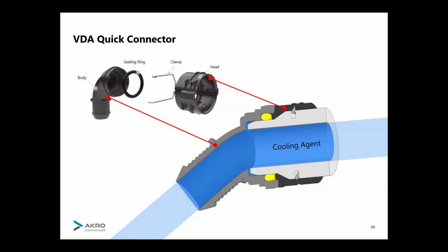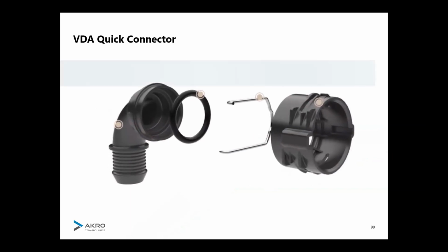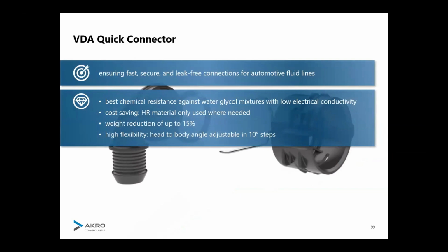And so you have combined it with a sealing ring and with a clamp. But in the end, you can really focus on mechanics and on toughness in this area, and on price. And you also have higher functionality because you can adjust the angle from head to body in 10 degree steps. So when normally you would have needed a new mold for every different angle, you just adjust them slightly differently. So it's also an additional benefit.